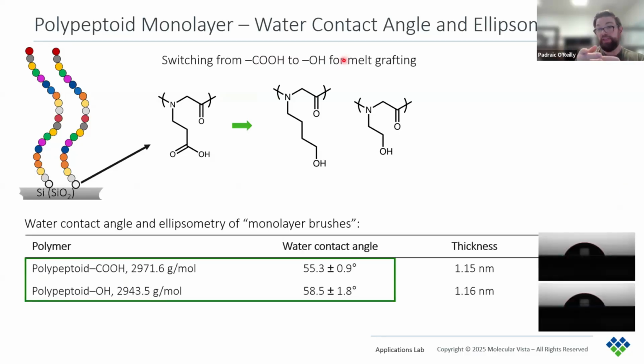Now, the interesting thing is here, they actually redid the water contact angle and ellipsometry measurements for this new OH monolayer sample, and it showed very similar results to those found on the carboxylic acid sample, and that sample obviously did not have a monolayer. So it's not possible to discern from these results if there actually is a monolayer or not. It would actually suggest that there's not.